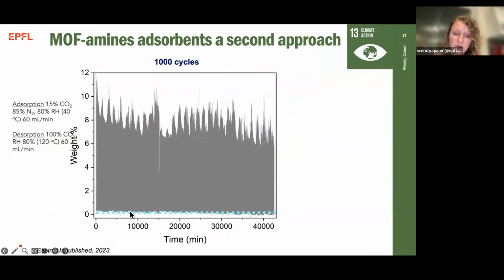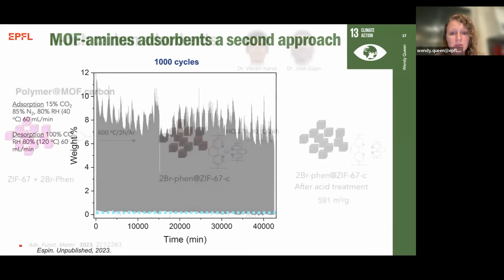But what I want to point to is that over 1,000 adsorption and desorption cycles, we see a very flat baseline. This is really important because if you see a decrease in your baseline, it's because your amines are leaching, so you're losing them. If you see an increase, it's typically because you have CO2 that is binding irreversibly, which means you're forming other species like linear or cyclic ureas. And so we don't see either of those things, which would imply that our material has very good cyclability over these 1,000 cycles.